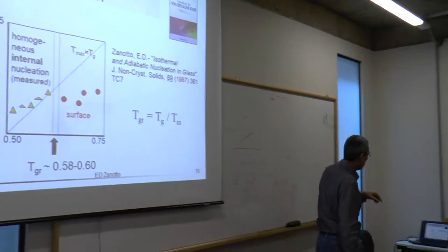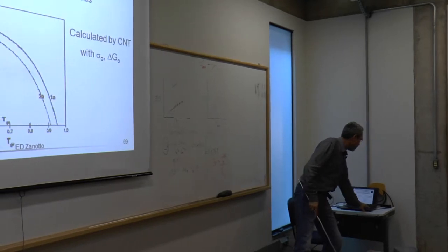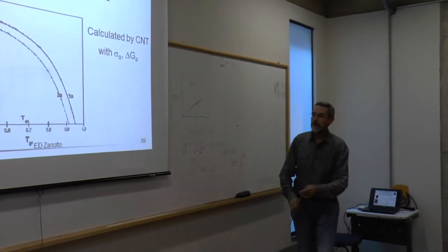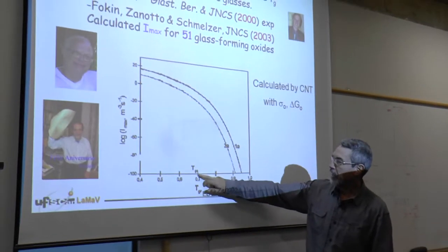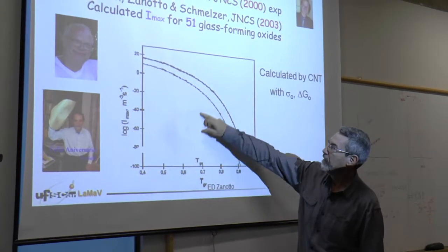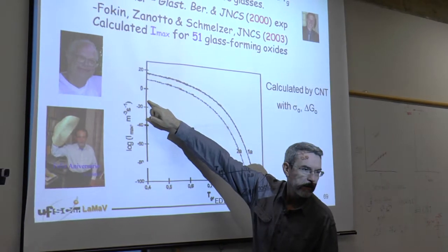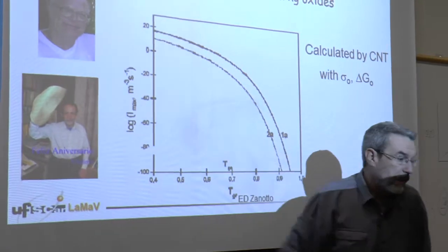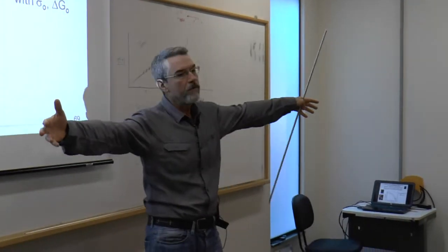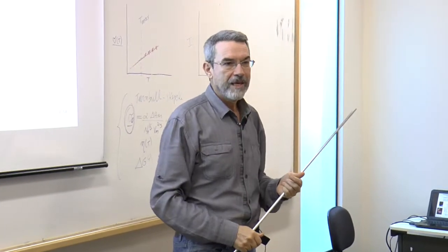If you remember, I'm going to show the previous plot. Here. Oh, sorry, this one. If their TGR is high, like say 0.7 or 0.65, the nucleation rates are very small. They're too small, so we cannot measure. You have to wait for years or have a sample of the size of this room and be patient for one or two or three, half a dozen nuclei to form. And this is very interesting.